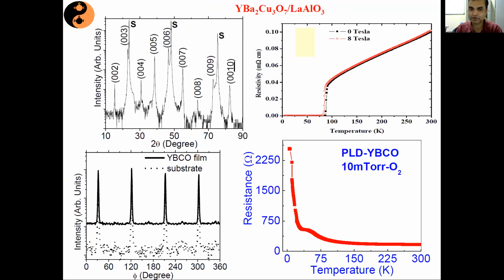Okay, the role of oxygen partial pressure. Oxygen partial pressure is a very important parameter. For instance, it is shown here for YBCO. You can see that this is grown on a substrate like LaAlO3. Beautiful film, 002, 3, 4, 5, 6. No other film peak is observed. Why? Because this is epitaxially grown. You have an oriented film, so you will not be able to see any other HKL.